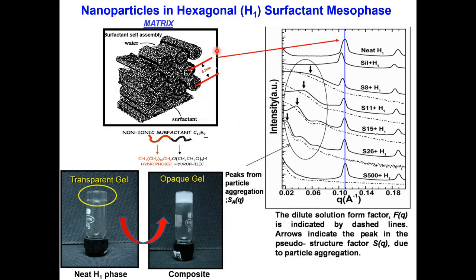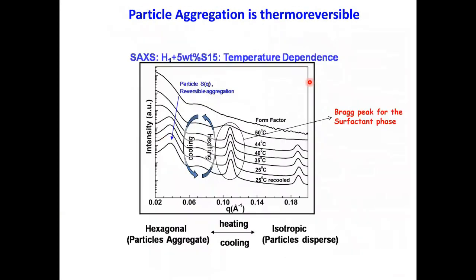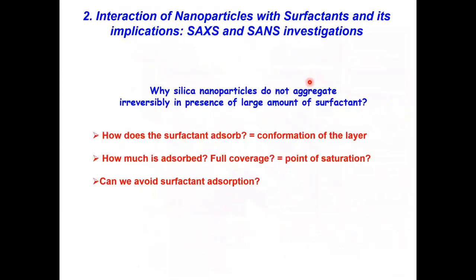Now, the center to center spacing between these micelles can be given by this peak, which is 5.7 nanometer. I can just look at the Q value and pull out the D spacing. But if I start putting in these silica nanoparticles, numbered 8 nanometer, 11 nanometer, 15, 26, you can see there is this peak which emerges over here, which is a structure factor peak that comes due to the particle-particle aggregation. I can monitor this peak and pull out structure factors. Okay, I'll just skip this data.